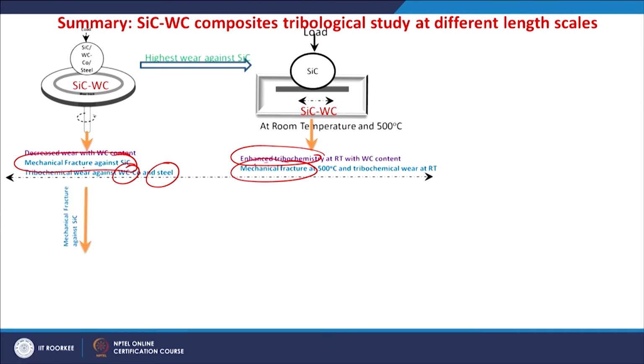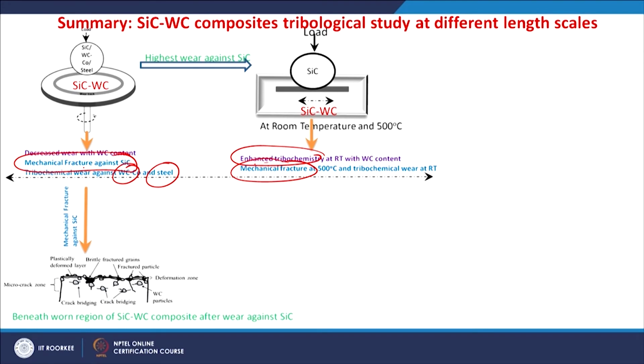So, in order to understand the origin of material removal, we selected the silicon carbide tungsten carbide composites for the study in subsurface regions. We selected the composites worn against the silicon carbide only. The reason again is that it is only the mechanical fracture, there is no tribochemical layer. So, it is easy to understand the origin of the material removal from the beneath region. So, subsurface regions,